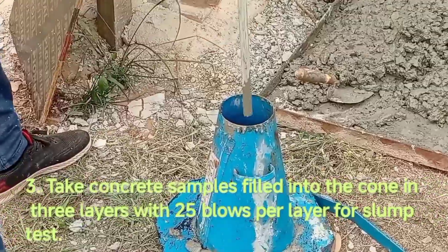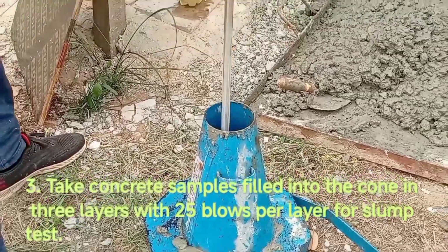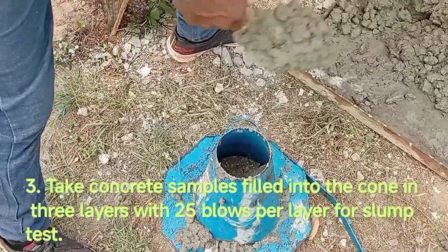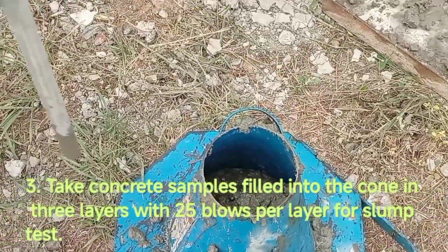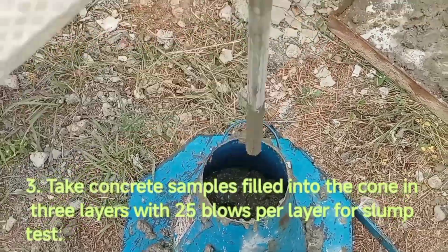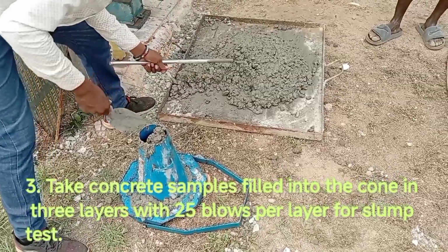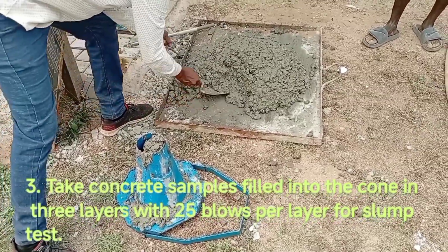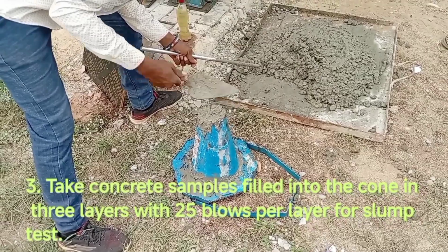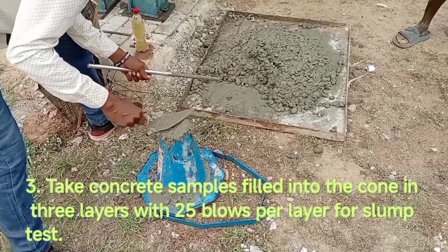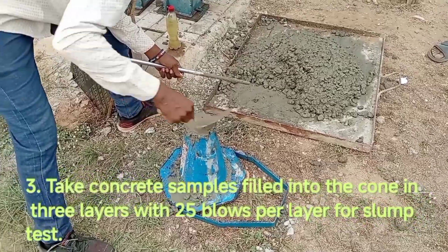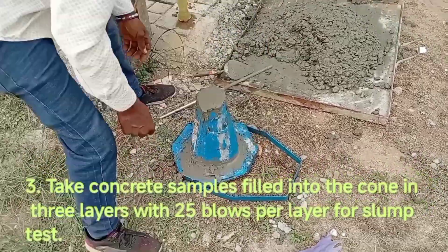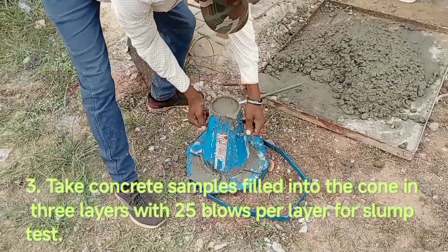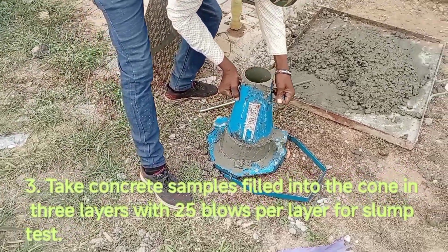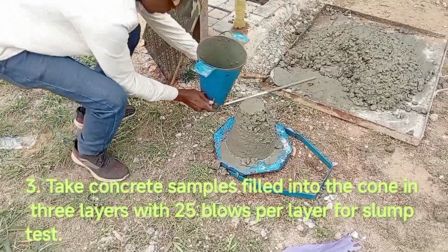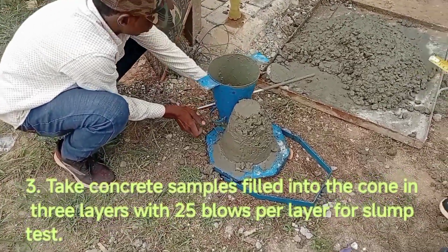So now look at the slump test being carried out. See the compaction, that's the layers. They put this in layers, and the concrete will continue until it gets full, and you are sure that this is what it's supposed to be. 25 blows, we call it blows. Ensure that you have proper compaction. Then when it is full, you trim, and then you can now remove the cone gently. You leave the cone gently, and then you measure.